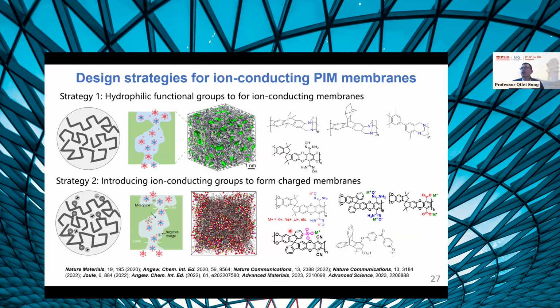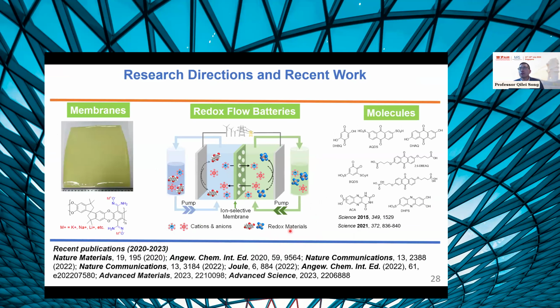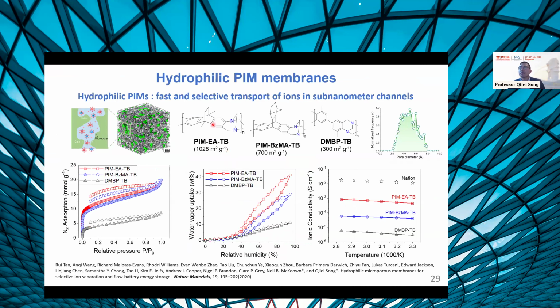Now I want to share some of the detailed results with you. One of the works we did is to use these hydrophilic Tröger's base polymers. This was initially developed by Professor Neil McKeown 10 years ago. They were initially used as gas separation membranes. These PIM polymers can have very high surface area. You can see that PIM-EA-TB has a high surface area, about 1,000 square meters per gram.